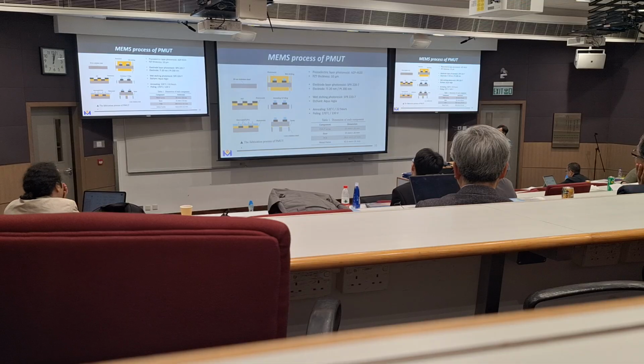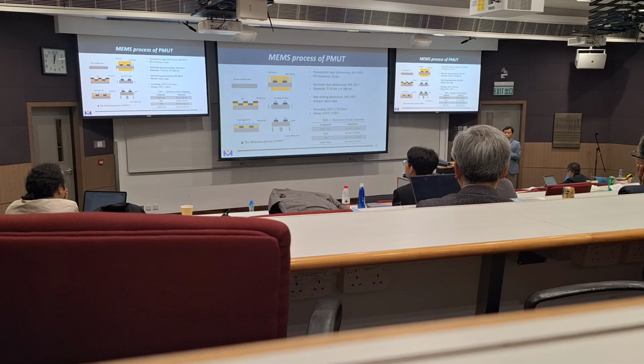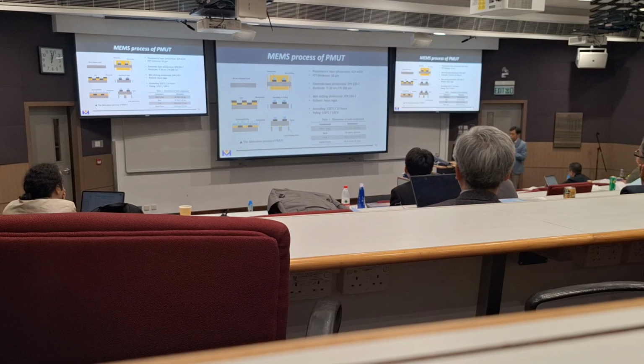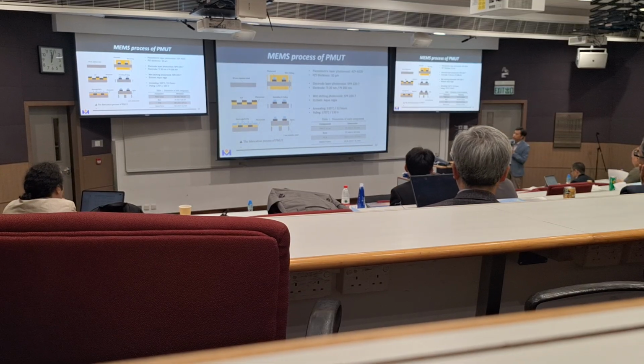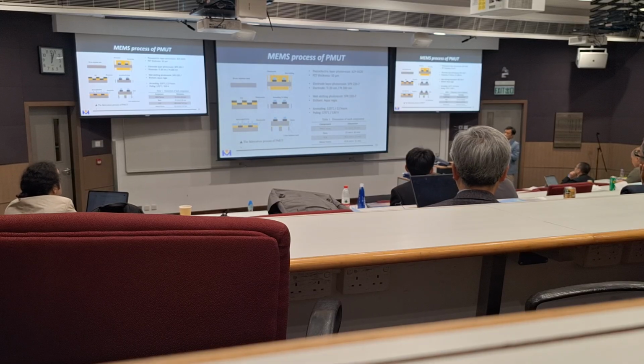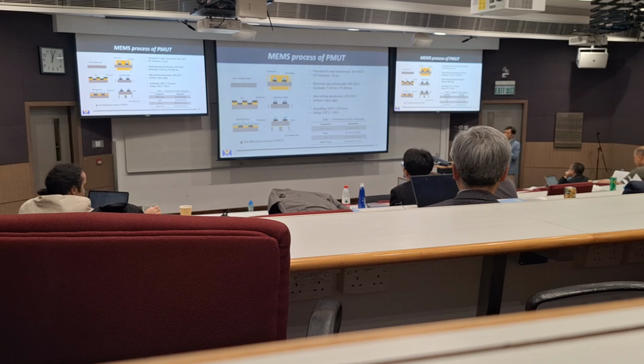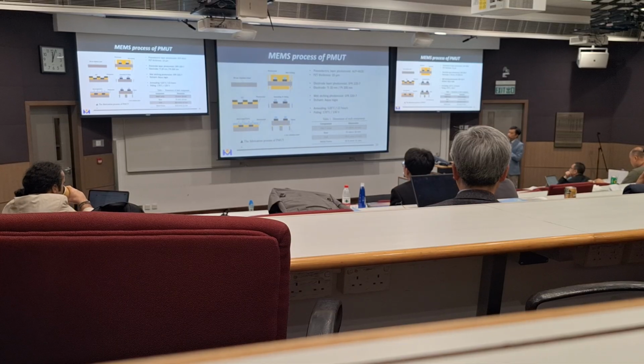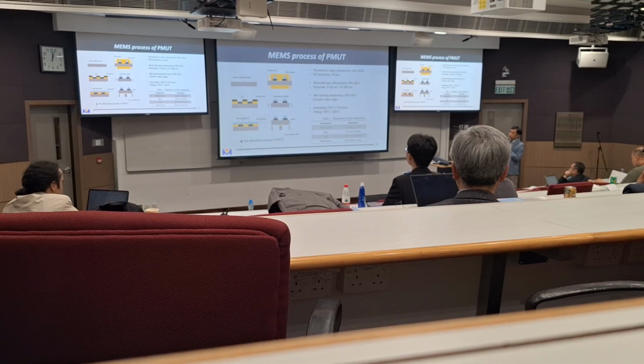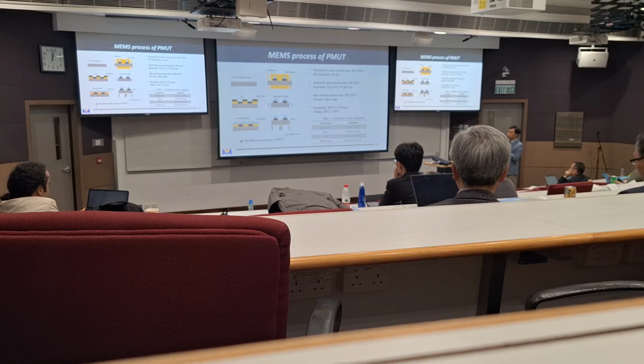The fabrication platform has been developed in my lab for the past 20 years. In the very beginning, we used this platform to fabricate energy transformers and then energy harvesters. I spent probably more than 10 years working on energy harvester development, and the transducers we typically make are around a centimeter in size, so we can have enough power output. Although our transducer is bigger, the fabrication process is still quite typical micro fabrication